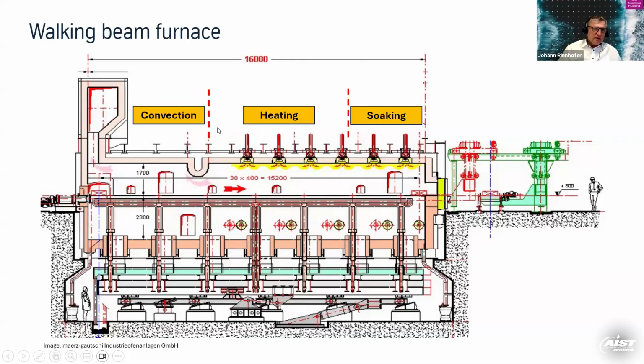A lot of heat we are transferring in the heating zone, which is in the middle here. We are heating up the steel, you know, we have still a relatively low steel temperature, so it is a very, very good condition to transfer a lot of heat. This is a high temperature difference. We have large burners on the top and also on the bottom of the furnace.